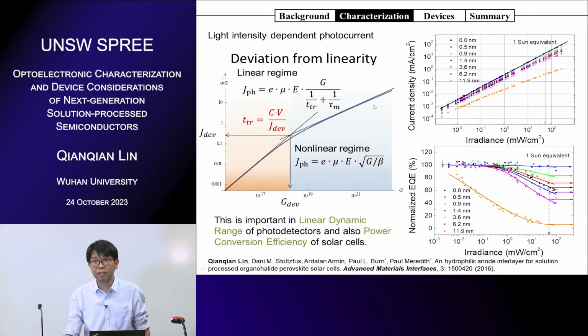How can we measure mobility further? We do light intensity dependent photocurrent measurements. This is another steady state measurement. We just use a CW laser to excite our devices and we get photocurrent. Under low photogeneration regime, the current normally goes linearly with photogeneration. But under very high illumination, the photocurrent may deviate from linearity because more carriers get recombined. So the recombination region is at much higher intensity than the linear region. From the kink, we can also get the transit time, because if the carriers cannot move fast enough, then they can meet each other and get recombined.